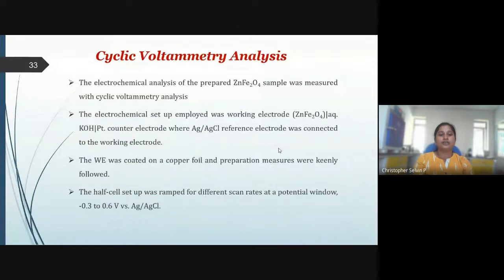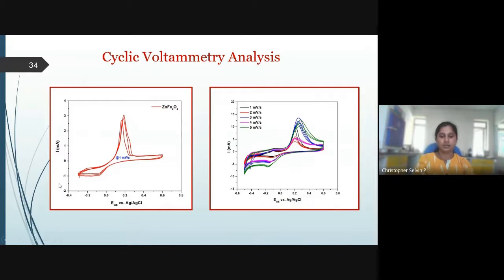So for this analysis, the electrochemical setup employed was a working electrode, aqueous KOH, and a platinum counter electrode. For the purpose of nullifying the effect of interaction of the working electrode with other components, we are connecting a reference electrode, that is AgCl, with the working electrode. For the working electrode, we employed copper foil. On the copper foil, the working material was coated and used for analysis. The setup was ramped for different scan rates at a potential window like minus 0.3 to 0.6 versus the reference electrode.